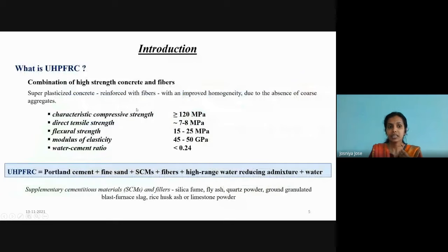So what is basically this UHP FRC? We can say it's a combination of high strength concrete as well as fibers. It's a superplasticized concrete which is reinforced with fibers, and it has improved homogeneity due to the absence of coarse aggregates. It has a characteristic compressive strength greater than 120 megapascal, higher tensile and flexural strength, modulus of elasticity comparable to that of concrete, and a lower water cement ratio, less than 0.24.